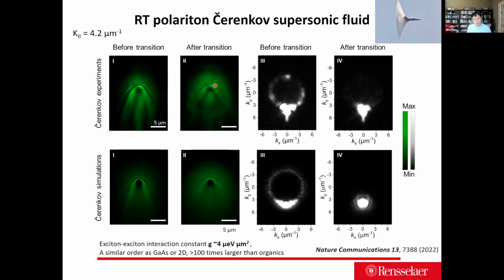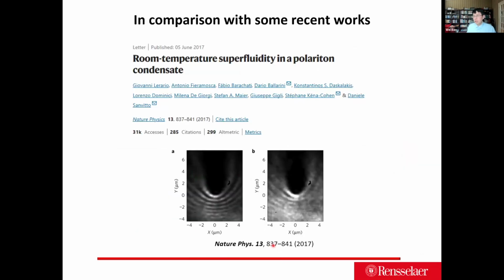By measuring the linear opening of the wavefront, we can extract the interaction constant, which is about 4 micro eV per micrometer squared, a similar order to gallium arsenide or 2D material, but 100 times larger than organic. In comparison with some recent work on superfluidity in organics in the Nature Physics paper done by my colleagues Stephane Kena-Cohen, Dario, and Danili, in the supersonic regime, because of the limits of the organic material, they don't show as nice a linear wavefront opening as in our perovskite case.